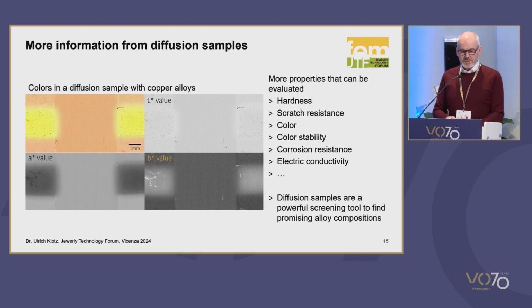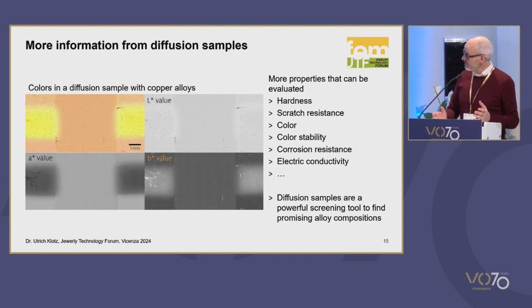We can also get more information from these diffusion couples. So the pictures here are showing on the upper left side the diffusion couple. So the 3 copper alloys, you can identify them from the different colors. And now just from the image, I can extract the color values, L, A and B. So I can match the composition with the color. I can also match the composition with the color after a corrosion test.